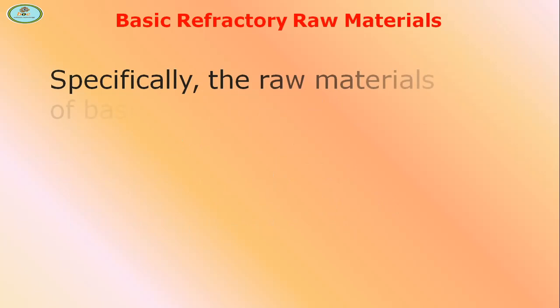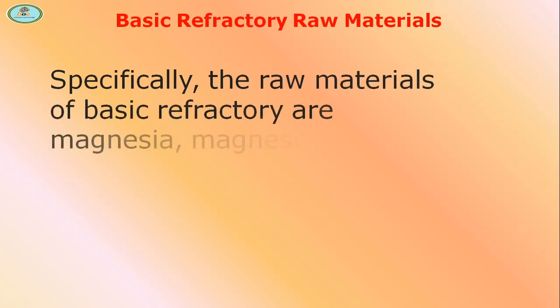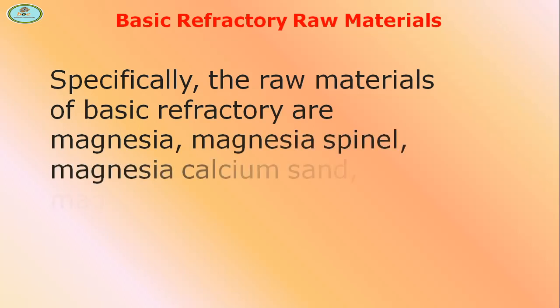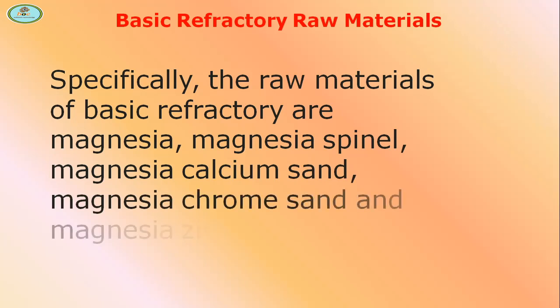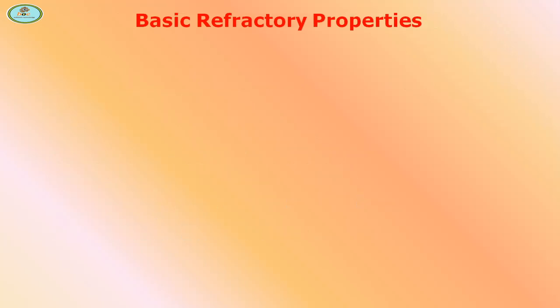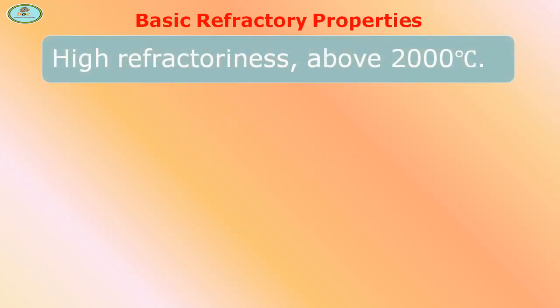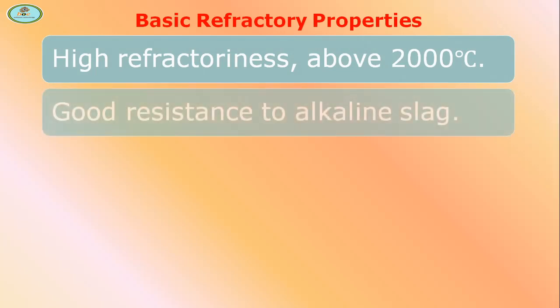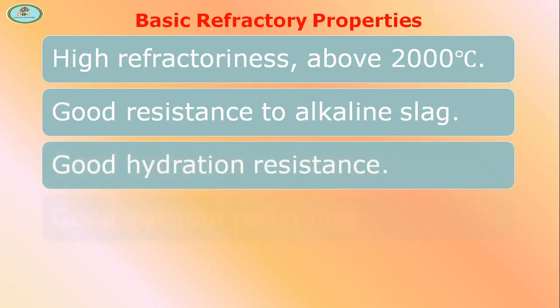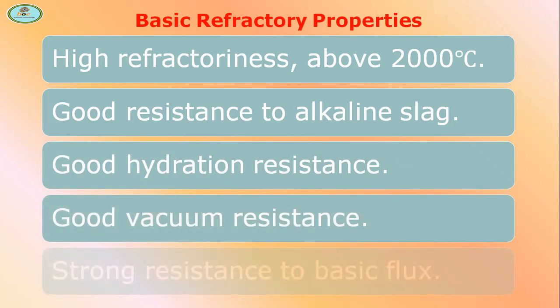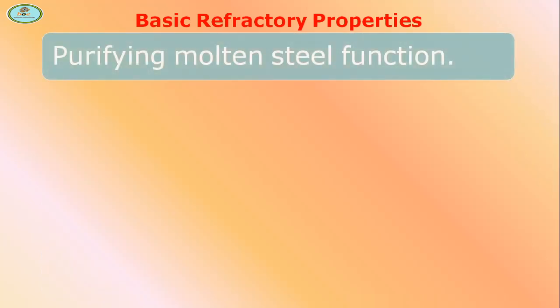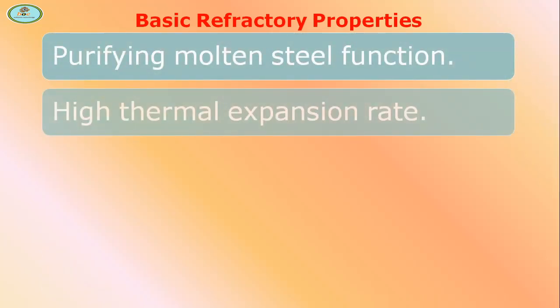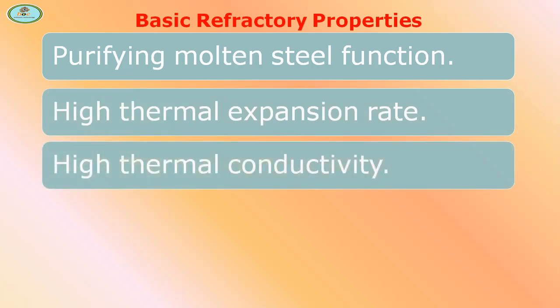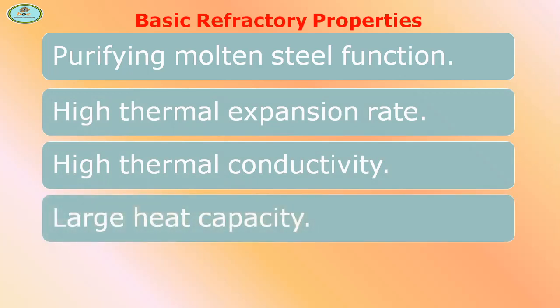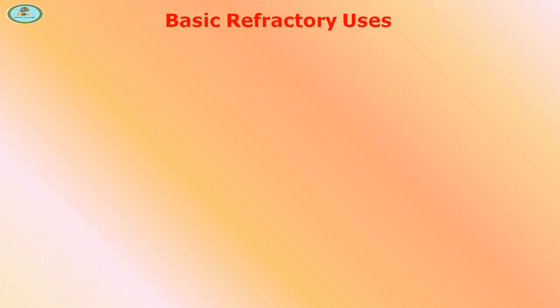Specifically, the raw materials of basic refractory are magnesia, magnesia spinel, magnesia calcium sand, magnesia chrome sand and magnesia zirconium sand. Basic refractory properties: high refractoriness above 2000 degrees Celsius, good resistance to alkaline slag, good hydration resistance, good vacuum resistance, strong resistance to basic flux, purifying molten steel function, high thermal expansion rate, high thermal conductivity, large heat capacity, poor thermal shock resistance.